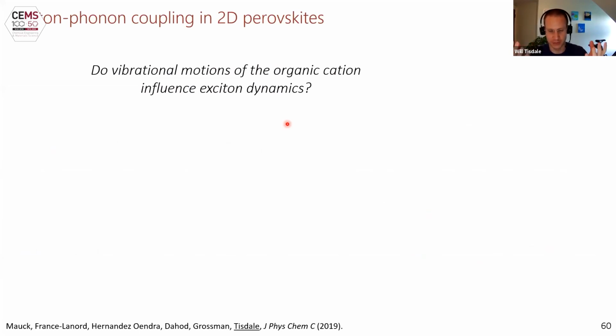So we've got this picture of a material where electronically the organic subphase is very decoupled from the inorganic subphase. The band gap of the material is determined entirely by the inorganic layer and what its thickness and composition is. And from a structural standpoint as well, we saw that you can really view these a lot like composite materials, that the organic phase can undergo its own structural transformations without significantly affecting the inorganic subphase. So a lot of these indications are that the organic and inorganic layers within this natural quantum well structure are largely decoupled from each other.